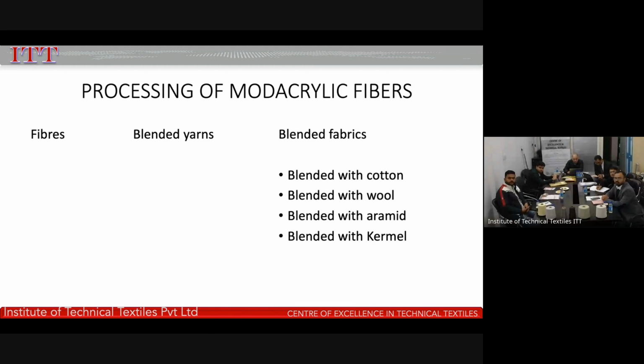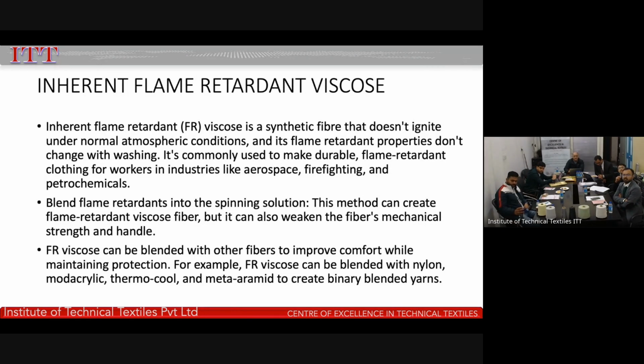Now this, as we say, fabrics, blended yarns and blended fabrics. It can be blended with cotton, wool, aramid, Kermel. Then we have another fiber, which is the flame retardant viscose. Now here the additives are added into this viscose during the spinning stage, and it is made inherently flame retardant. This can be blended with a variety of fibers, nylon, modacrylic, thermocool, metaaramid, antistatic yarns to create diverse blends.